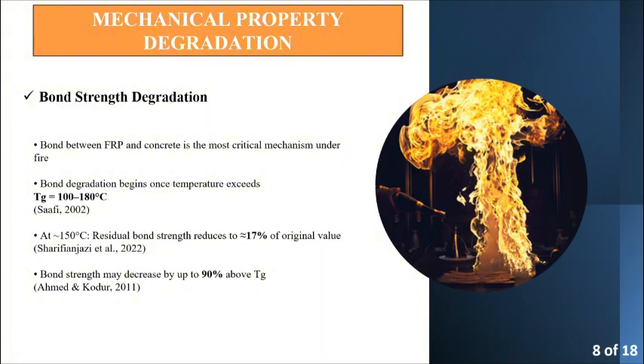Bond strength degradation is one of the most critical problems under fire exposure, because in FRP reinforced concrete, the bond between FRP bars and the surrounding concrete is essential. Why? Because this bond allows the reinforcement and the concrete to work together as one composite system. However, when the temperature increases and reaches the glass transition temperature, which we mentioned, Tg, the resin inside the FRP begins to soften. Once the resin softens, the bond between the FRP and the concrete weakens significantly. So the adhesion reduces and the load transfer between the materials becomes less effective.